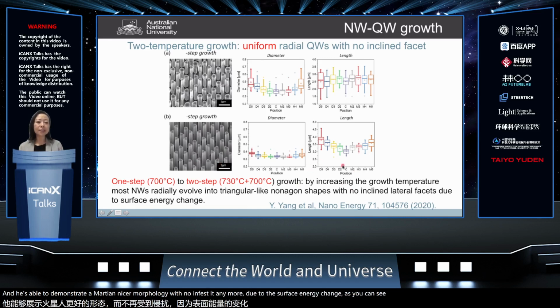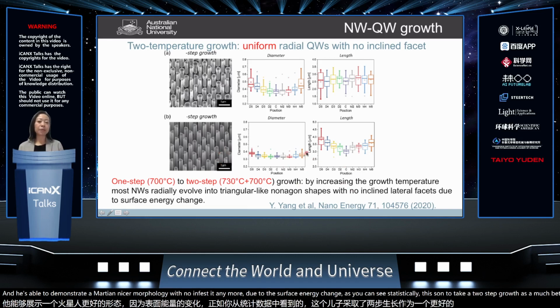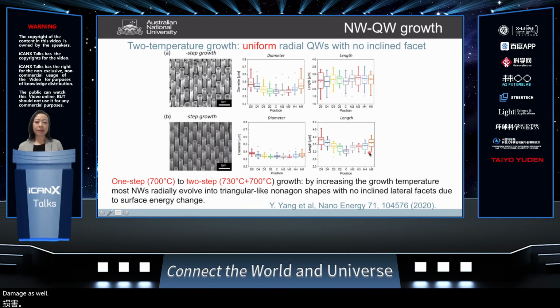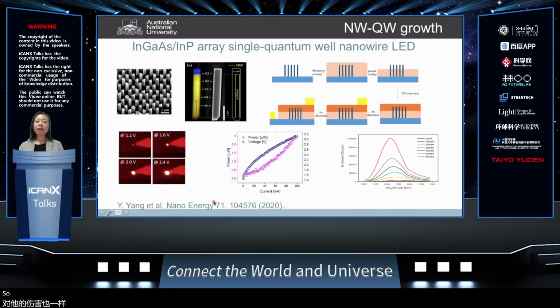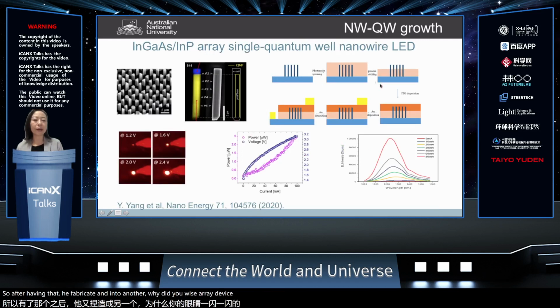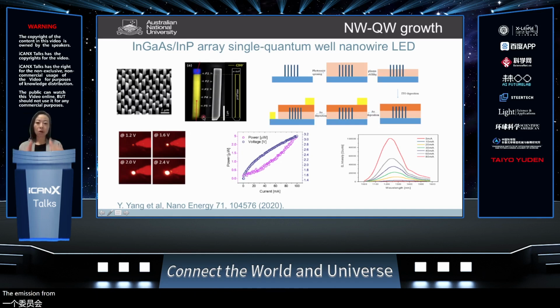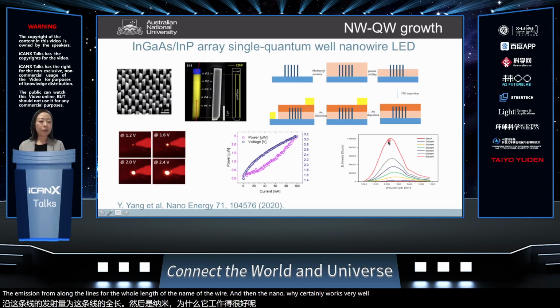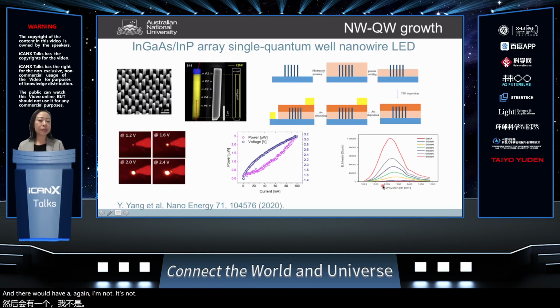As you can see statistically, this two-step growth has a much better uniformity in terms of the diameter as well as the length. After having that, he fabricated it into a nanowire array device by doing planarization and contacting. And then you can see this is the cathodoluminescence measurement from our nanowire, showing very uniform emission along the whole length of the nanowire. The nanowire certainly works very well, and we have, again, quite nice wavelengths at about 1.3 micron.